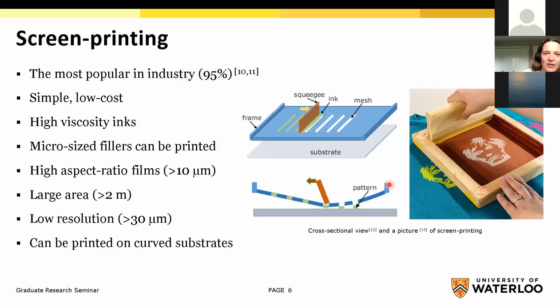The other question on screen printing is that the viscosity of the ink has to be more viscous for screen printing compared to some other printing technologies. Yes. Sometimes it's even called paste because it's really viscous. Other printing technologies have a really short range, and they usually use really low viscosity inks. They are even in solution form. But screen printing ink is really viscous, and that's needed, because as you can see, this ink, while staying here on the gap on the mesh, is not being dropped to the substrate, it's just staying there.